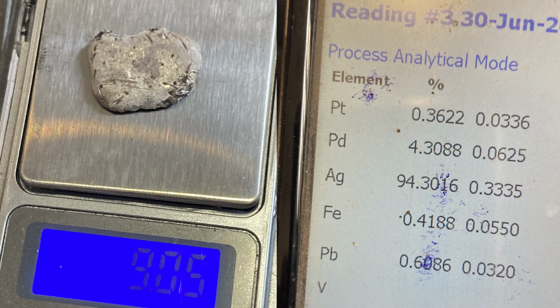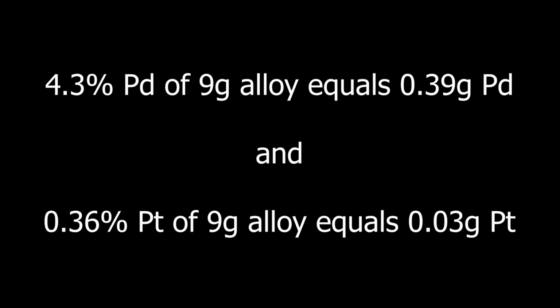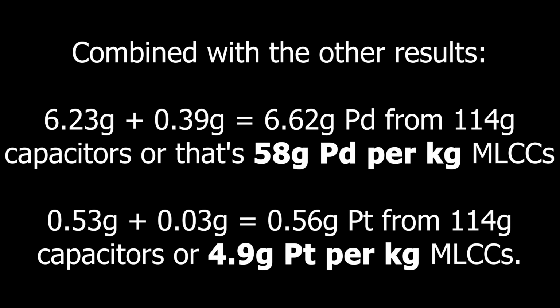XRF of the button. 4.3% palladium of 9 grams alloy equals 0.39 grams palladium. And 0.36% platinum of 9 grams alloy equals 0.03 grams platinum. Combined with the other results, 6.23 grams plus 0.39 grams equals 6.62 grams palladium from 114 grams capacitors. Or that's 58 grams palladium per kilogram MLCCs.